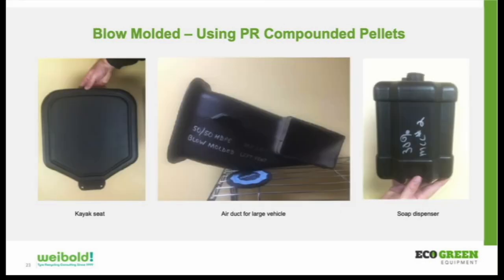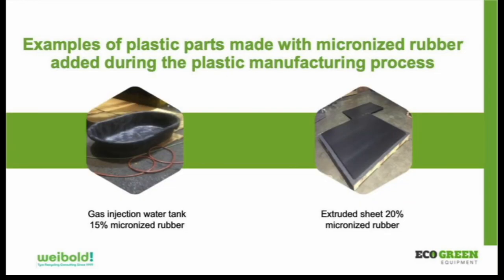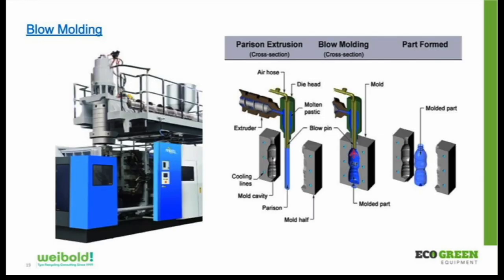Blow molding. Here's a few examples of blow molding. We have a kayak seat on the left, an air duct in the middle, and a small soap bottle on the right. The interesting thing about blow molding with this material is that in blow molding, they're used to using a lot of recycled content. But the challenge with that is, if I go back to the blow molding process, where this parison comes out, the parison drip or parison stretch is very hard to control if you don't know exactly what your melt flow is. And when you're using a lot of recycled content, the melt flow is going up and down. It varies all over. So melt flow control or parison stretch is very difficult to control.